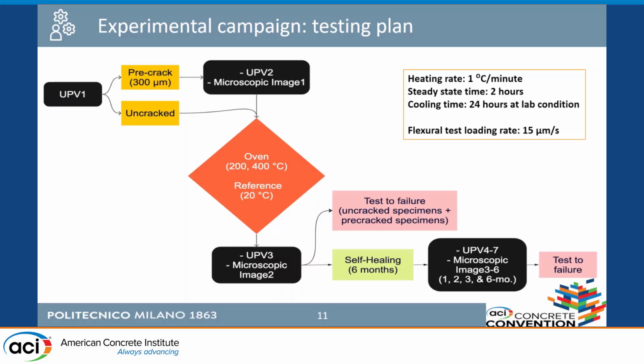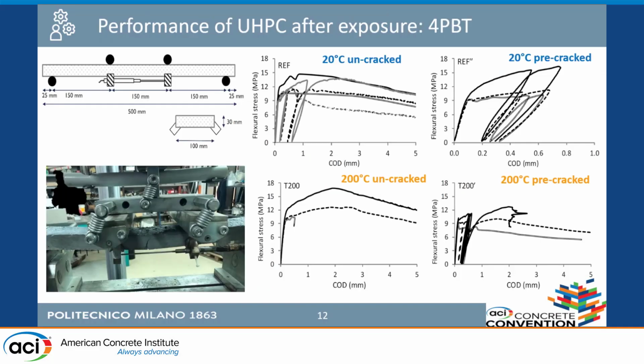I would like to add just that we also performed ultrasonic measurements, because ultrasonic measurements are non-destructive, so we can follow the evolution with time, and the ultrasonic pulse velocity gives us an indication about the stiffness of the material. So let's go on to the test.